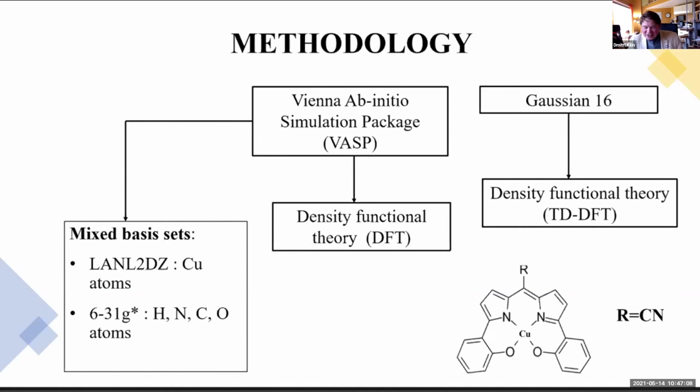Right. But it's very easy to go into the archive file and look at the calculated local magnetic moment, or plot the charge density. You take the difference and see that the extra electron or extra hole is localized on copper. It is much harder to get this in VASP for this system, but much easier from the local basis set calculations with Gaussian. I think Lola was checking these charges in Gaussian, seeing the difference in the charge on the copper when she varies the charge on the entire molecule. Yes, it's a good question. When you talk about the charge, it's a good idea to confirm your results with computational data. Thank you for the discussion.